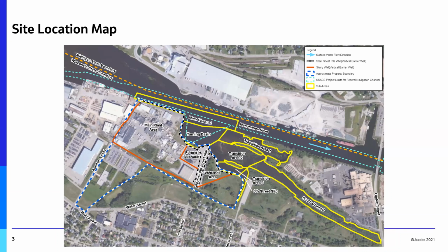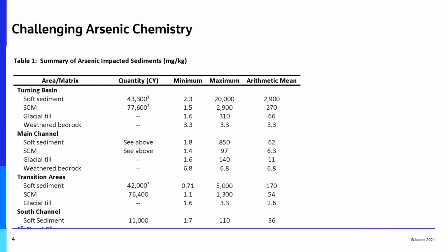So how do you effectively manage that in a remediation project where you're trying to take arsenic impacted sediments, bring them to the dock, dewater them, and, because we're very congested here, this was about 1.5 acres, export these to a municipal solid waste landfill with a non-hazardous classification? And what that means in the United States is that your toxicity characteristic leaching procedure, or TCLP, value is less than 5 milligrams per liter arsenic. So we needed to achieve all of that in basically 72 hours to get that stuff off site to avoid additional site congestion. So part of the challenge with this, as I indicated earlier, was the variability.